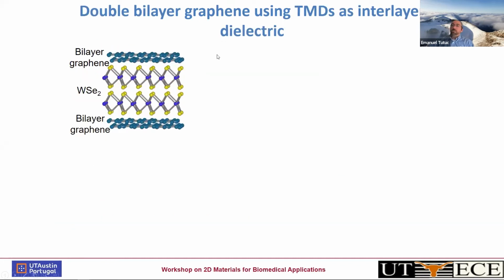So let's examine one such heterostructure that's a bit more complicated than the one we discussed earlier. So this is bilayer graphene with the tunnel barrier here in between. So tungsten diselenide is going to be a supporting actor here. It's not going to be a semiconductor, but simply a tunnel barrier. And one thing I would say is that these two lattices are rotationally aligned, so that ensures that electrons in one layer have the same momentum as the electrons in the other layer when they tunnel.